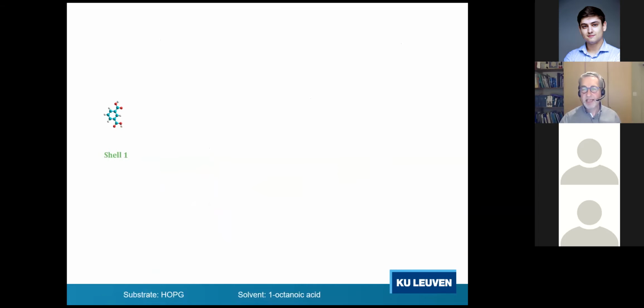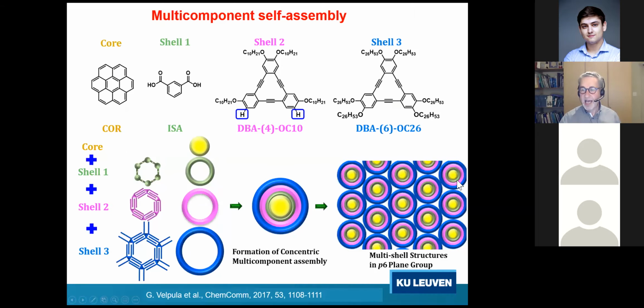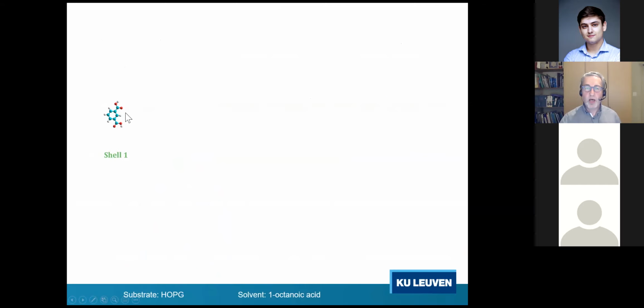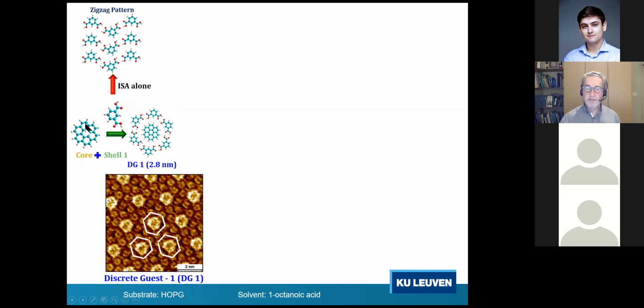But let me explain it to you by showing images. Now, it's important to say that of these 4 components, if you bring them by themselves, just as a monocomponent on the surface, none of them will actually form a structure that relates to the targeted structure over here. So if you would just take this shell 1 molecule, it would form, as modeled, this kind of network on the surface supported by hydrogen bonding. However, if you add coronene to this shell 1 molecule, and here I indicate it with the model, this kind of motif is formed where you have a coronene molecule surrounded with 6 of the isophthalic acid molecules.